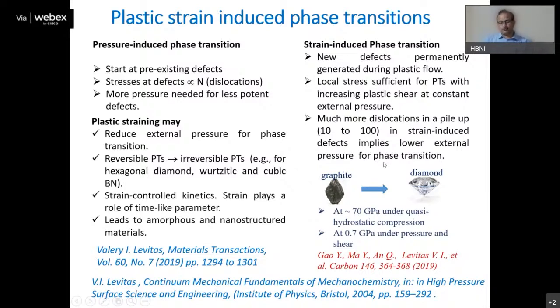So one thing is that you can get very low transformation pressures, I mean macroscopic pressures. And another possibility is that it can change reversible phase transitions to irreversible. Because of the straining under the plastic strain, basically the barrier between the initial and daughter phase can drastically reduce. So the kinetics of this transition becomes so fast that only strain actually describes the kinetics. As soon as you increase strain, there will be some transformation, and you will get an increase in the concentration of the daughter phase. So now your kinetics can be described based on the plastic strain. This is one of the key things to study in plastic strain transitions.